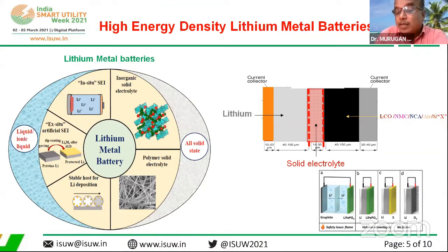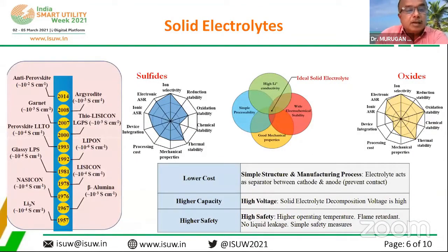So you can think about lithium with the lithium insertion electrodes, and metallic lithium to sulfur, and the future is the lithium oxygen battery or lithium ion battery concept. So what we really need is finding a suitable solid electrolyte. That's the biggest task. People have struggled hard for the last 57 years. It's not new to the world, but from almost 1957 to the present, 2014, there was one big breakthrough afterwards. So several oxides, sulfides and nitrides came into the picture. But out of all the solid electrolytes, still it's a competition between the sulfides and oxides.